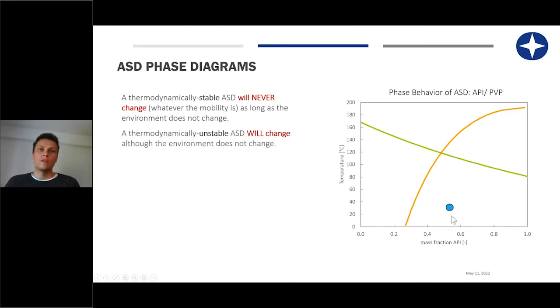On the other hand, if we have a drug load that is above the critical equilibrium solubility, we will definitely see crystallization after infinite storage time. It's only a matter of time. This means we have to ask ourselves, how far are we below the glass transition and how far are we away from the equilibrium solubility? And then we know whether there will be crystallization in a short period of time or in a long period of time.